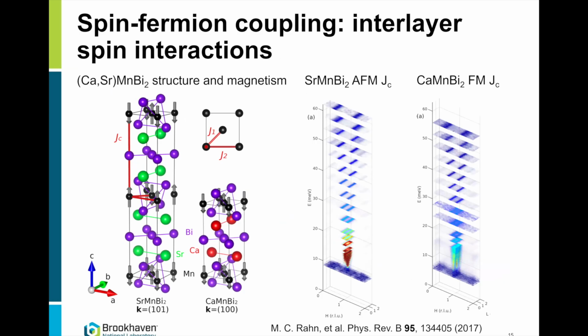Now, of course, the simple way to quantify the interaction as a function of material composition is to just measure the interlayer coupling as a function of varying material compositions. This has been done also by the Oxford group. So this is Andrew Boothroyd's group measurement in strontium manganese bismuth 2 and calcium manganese bismuth 2.